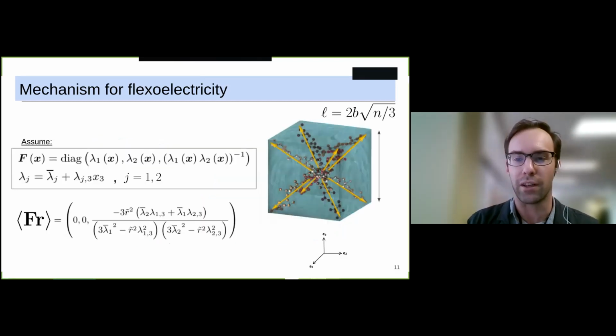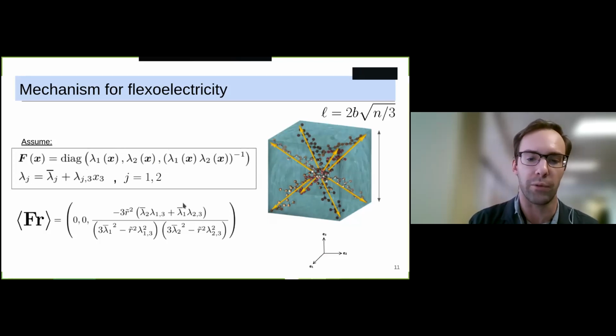elastomer networks. And so it turns out, of course, there are equations that go with this. Here, if we assume this simple form where I have principal stretches in the E1 and E2 direction, and those are varying with respect to the E3 direction, we can get a precise expression for what we expect the flexoelectric coefficient to be.